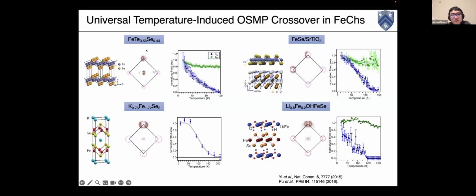And this OSMP phase actually is universally observed in these iron chalcogenide families, no matter whether they are single crystals or thin films, or no matter what their Fermi surface topology looks like. With increasing temperature, the spectral weight of the dxy orbital always vanishes, while the spectral weight of the dyz orbital still remains finite at high temperatures. This is the so-called temperature-induced OSMP phase.